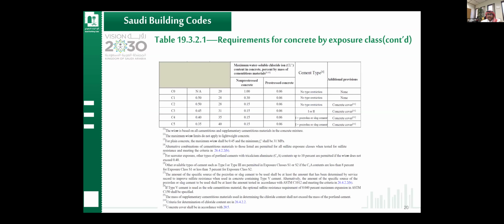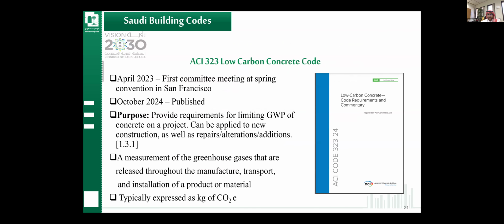This is a continuation of the previous table. This shows if you are in an area that requires the protection of reinforcement from corrosion, you may be C0. The higher the number, the more severe is the situation. So you can see that there is no requirement on the maximum water to cement ratio. But if you go to C5, then you are limited to 0.35, and the minimum compressive strength is 40 MPa. There are other requirements here. For example, you have additional provisions, concrete cover. You have to increase the cover to provide extra protection for your elements.